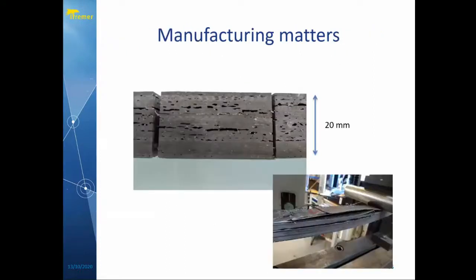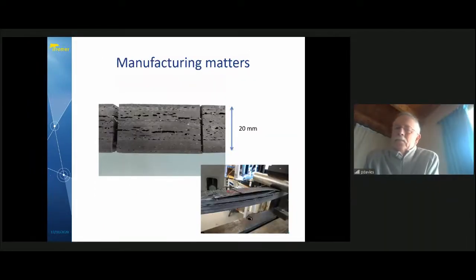The next slide, please. And as I'm sure most of you know, manufacturing matters. And one of the key issues we have is upscaling. We can do a lot of tests on small specimens. Our machines are set up for it. So we tend to test specimens in the 3 to 5 millimeter thickness range. But then when you go to 20 millimeters, 30, 40, 50 millimeters, the materials which you very often get are not the same materials as those you've been testing at small scale.